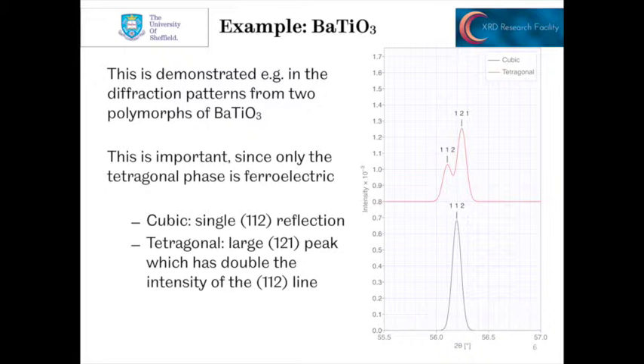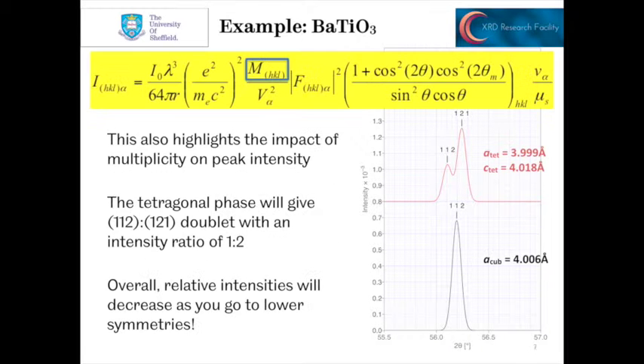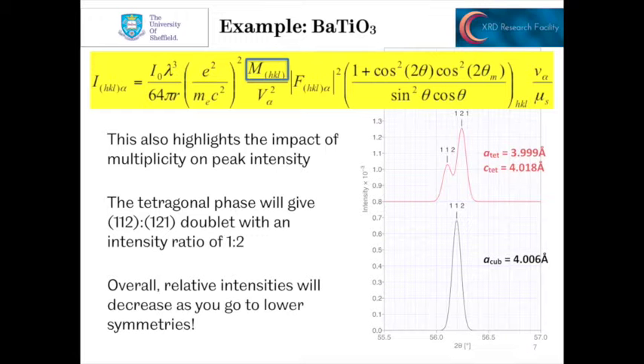You can see also the peak intensities are lower as well. We looked at in a previous video this equation for the intensity of a diffracted beam, and you can see the term I've outlined here for the multiplicity — this is built into the formulas for peak intensity. It really does highlight the impact: the 1,1,2 in the cubic phase is very intense, and as we move to lower symmetry going to the tetragonal system, we've got two peaks both of which are lower intensity. And we can see the 1 to 2 ratio there.